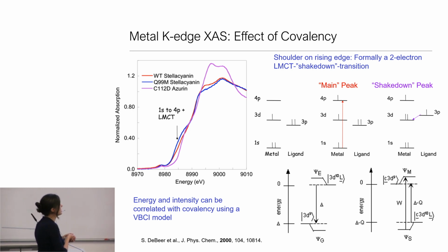And so in a state-based picture, the way I would see this is that I have a 3d9 ground state that is lowest in energy in the ground state, and a 3d10 ligand hole state. This is my LMCT state. And in the presence of the core hole, this ordering can actually change, and that gives rise to these so-called shakedown features. And so this is just something to keep in mind, that there are other features that can be superimposed on the rising edge that can be highly diagnostic also of the nature of the ligand.